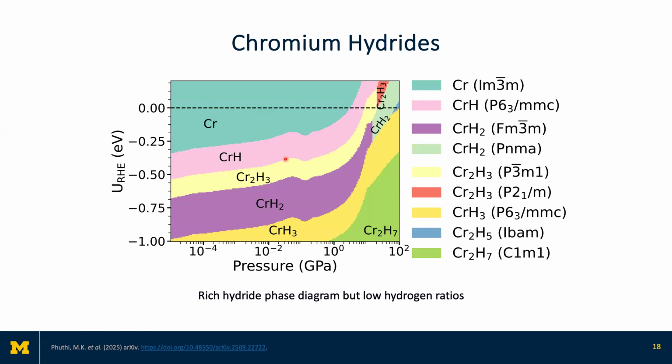If there's a kinetic barrier, then in principle, when you remove the electrochemical potential or remove the pressure, it will decompose back down to whatever is most stable. But whether that happens or not is determined by the kinetics. If there's a big barrier to that decomposition, it might stay as the hydride for quite a while. This is part of the consideration when you look at hydrogen storage: you form this hydride, how easily do you release that hydrogen?